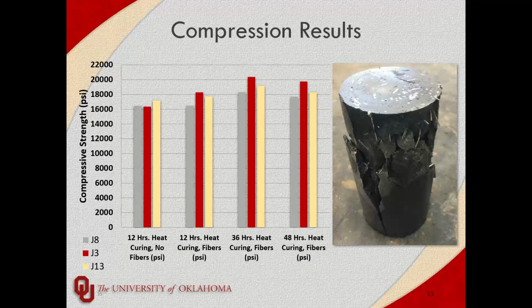But the one thing to note about those, and this was something that caused us no end of trouble because we really had to fight with the high range, was they were heavier than the Dramix fibers. So we did a lot of looking into how to optimize the flowability without compromising the way they float and making them sink, because that is a big issue with UHPC in general.